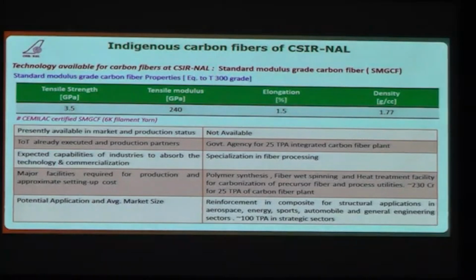For the technology, we have standard modulus grade carbon fiber, which I told is around 7 micron diameter, and this is equivalent to Toray T300 grade carbon fiber. This technology was developed with a strength of about 3.5 GPa, tensile modulus of 240 GPa, elongation 1.5, and a density of around 1.77. This product was certified through CEMILAC for 6,000 filament, which is typically used for aerospace application.